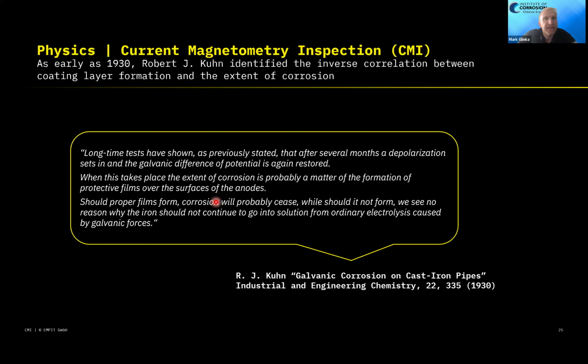He says, long-time tests have shown, as previously stated, that after several months, a depolarization sets in and the galvanic difference of potential is again restored. When this takes place, the extent of corrosion is probably a matter of the formation of, attention now, protective films over the surface of the anodes. Should proper protective films form, corrosion will probably cease, while should it not form, we see no reason why the iron should not continue to go in solution from ordinary electrolysis caused by galvanic forces.